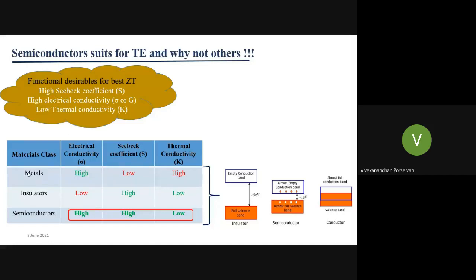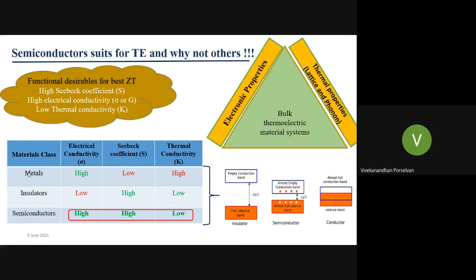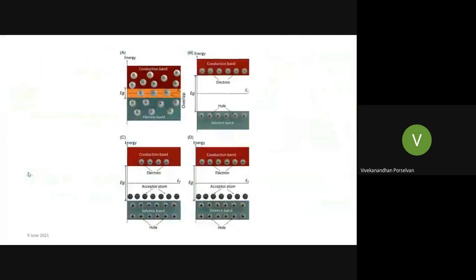Thereby the material can be highly conductive or highly insulative, or it can be semiconductive. In order to achieve the best ZT value in a bulk thermoelectric material, we should have a tailoring of transport theory, that is, band engineering. We should play with the electronic property phenomena and thermal property phenomena, thereby we can achieve a higher ZT.